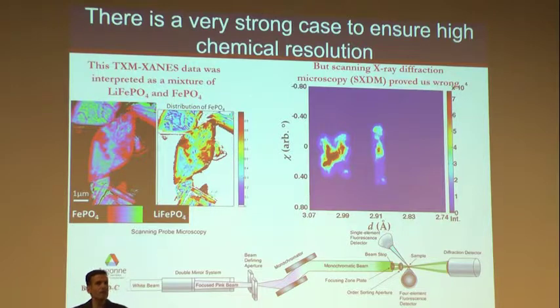But in terms of making arguments about crystallographic phases, technically, we're not getting that information. It's a local measurement, a local coordination sphere measurement. Typically, iron 2 and iron 3 are associated with lithium iron phosphate and iron phosphate, and we didn't see evidence of otherwise. There were two components. We did PCA, and there were two components in this structure. So we interpret this as a mixture of lithium iron phosphate and iron phosphate.